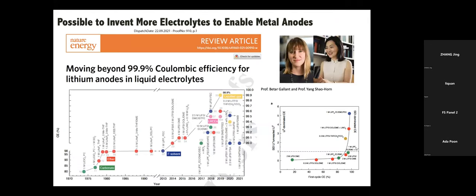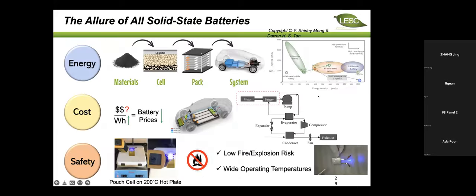So we then moved forward and did this Nature Energy article with Betar Gallant and Yang Shao-Horn from MIT. And the good news is that we have many electrolytes that can go towards 99.9% Coulombic efficiency for lithium metal anode. And we also showcase SEI is important: when you go above 99.6%, SEI becomes very important. And then we think this is a very, very optimistic pathway for us to think about. We can definitely develop 1,000-cycle lithium metal batteries in the near future, because we now have a much clearer understanding of what the limiting factor is in the lithium metal anode.